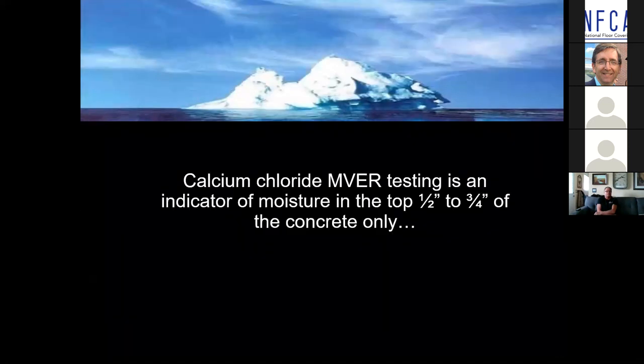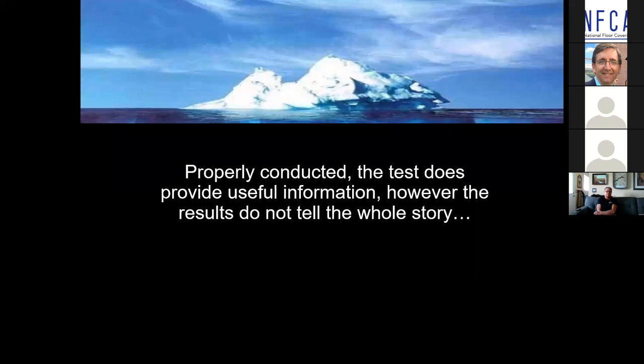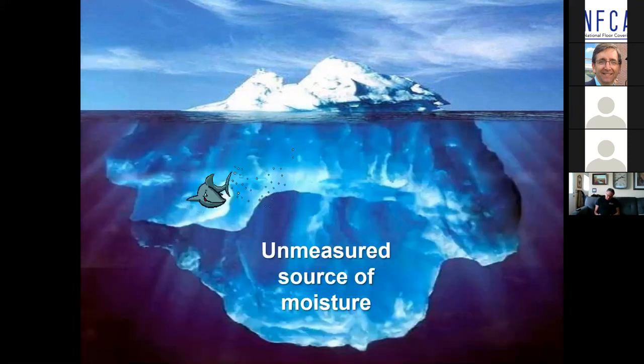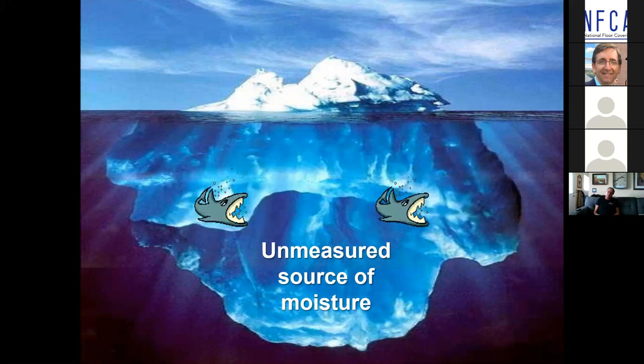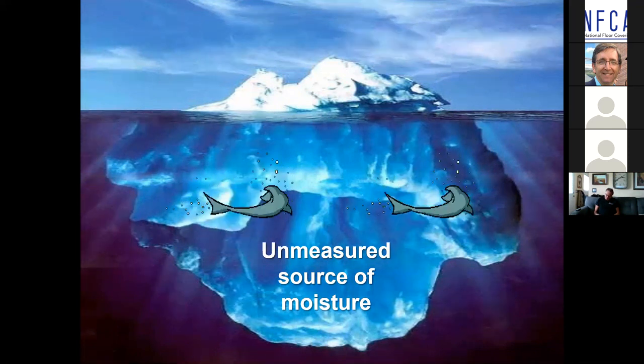So conducting a calcium chloride test is really the tip of the iceberg. I think it's still a valuable test. Alone, it's insufficient, but as a consultant, I want as much information as I can possibly get if I'm asked whether it's safe to put a floor down. But it doesn't tell the whole story. Underneath that surface is a potential reservoir, a considerably greater amount of moisture that the calcium chloride test tells us absolutely nothing about.